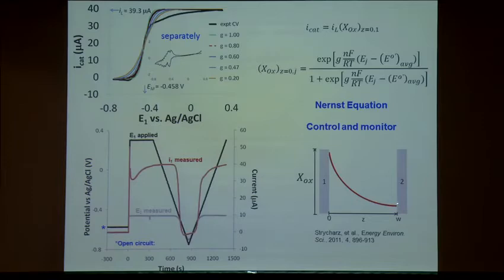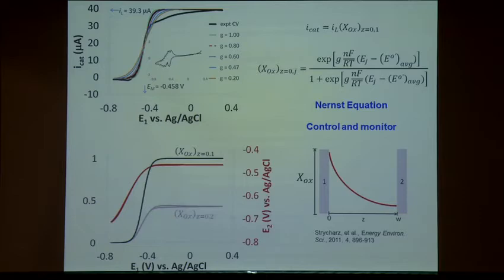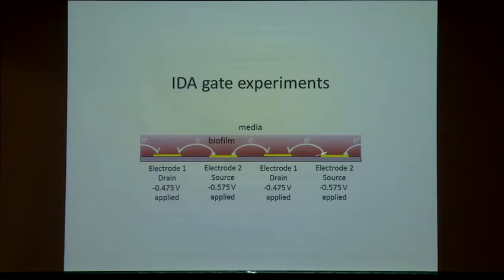And so the fact that I'm able to measure the potential at electrode 2 while I sweep the potential at electrode 1 is indicative of a redox gradient between electrodes 1 and 2. The redox gradient persists when I have current flowing, and then once the current, this is current going to electrode 1, goes to 0, the gradient is over. I'm going to go now to some IDA measurements here. These are probably a clearer demonstration.